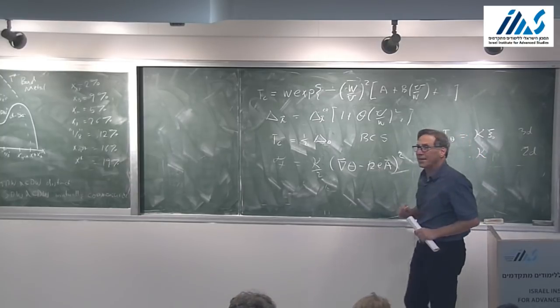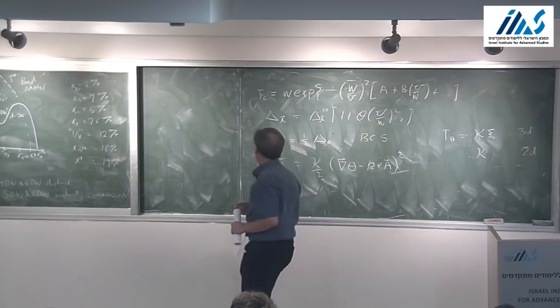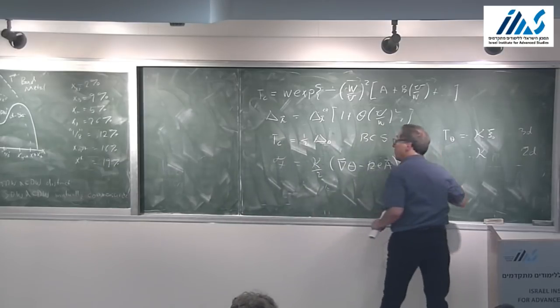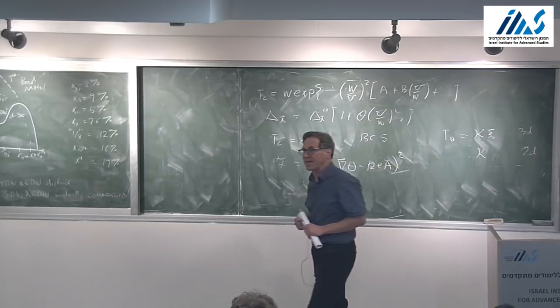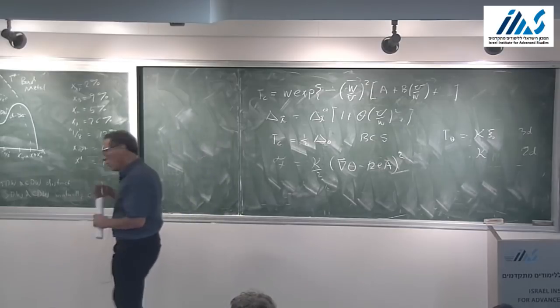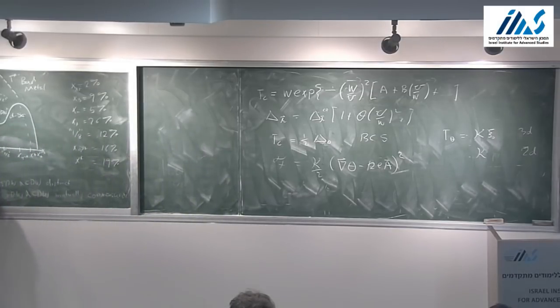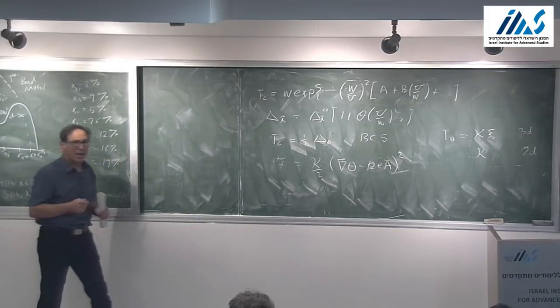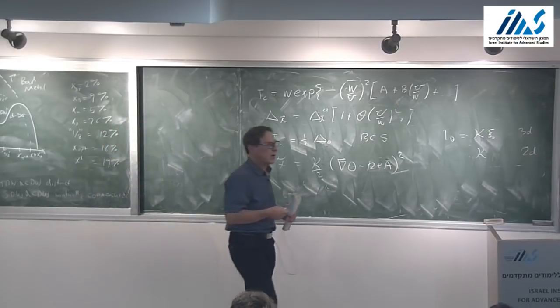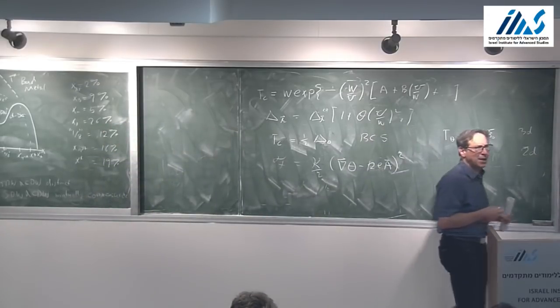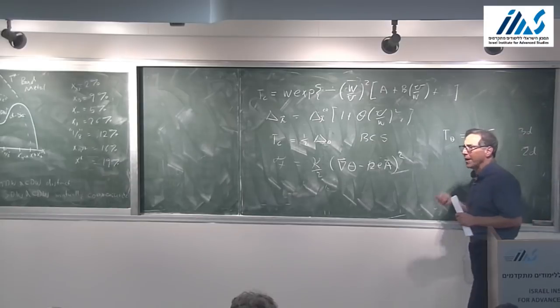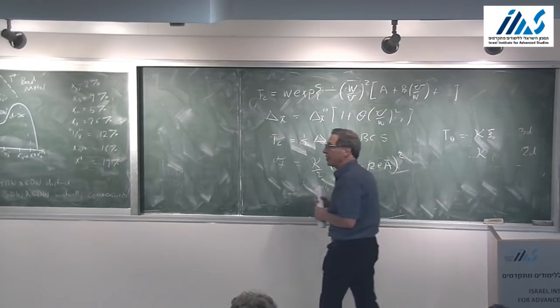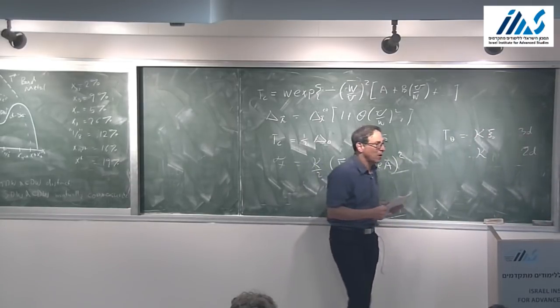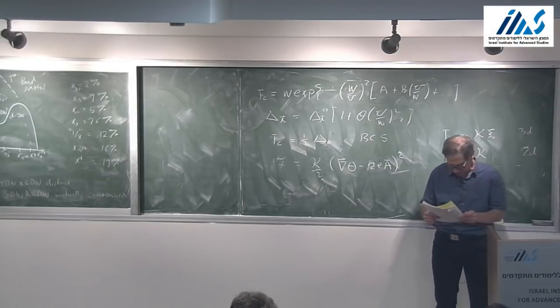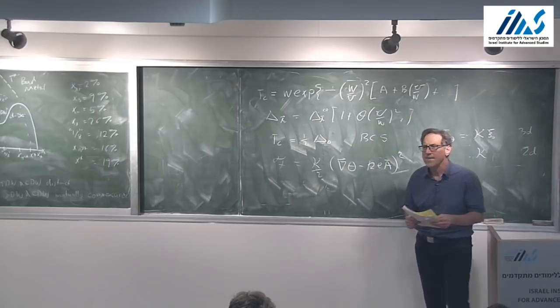However, in the cuprates, kappa turns out to be, or T theta turns out to be, very comparable to Tc. And so that tells us immediately that the superconducting state is order 1 different from normal superconducting states. It tells us that phase fluctuations, classical phase fluctuations of the superconducting order parameter, are an order 1 effect. Yeah?